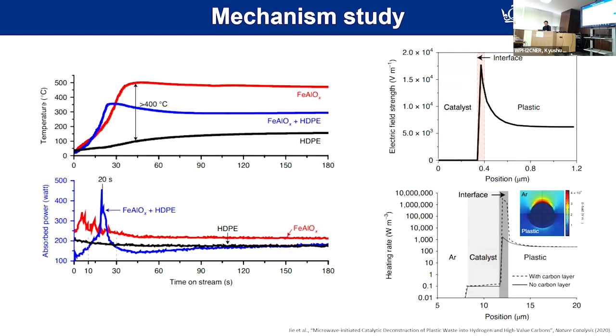And again, this is all based upon the materials' intrinsic properties in responding to the microwave. As you can see, polymers are generally transparent to the microwave, so they will not heat up in the microwave. That is a good thing, because under pyrolysis conditions, lots of side reactions generate so many byproducts, so it's very difficult to control. But under the microwave, since the polymers will not heat up, they can avoid self-decomposition under microwave conditions. Meanwhile, the catalyst we put in will efficiently respond to the microwave and heat up. And so when the large pieces of polymer meet or match with the catalyst, they will work.